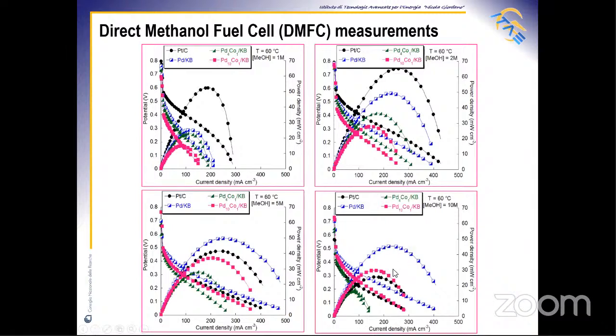decrease at 10 molar. On the other hand, the MEA based on platinum cathode achieves a power density of 65 milliwatt per square centimeter, feeding 2 molar methanol, whereas at 10 molar, the performance decreases to 25 milliwatt per square centimeter. So the high methanol tolerance properties of palladium and palladium alloy based electrocatalyst, as evidenced in the half cell characterization, are also demonstrated in direct methanol fuel cell.